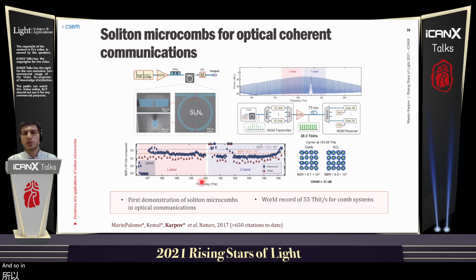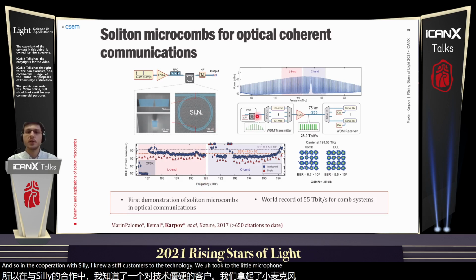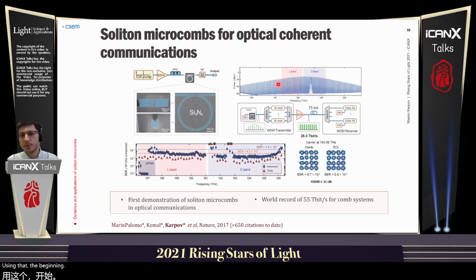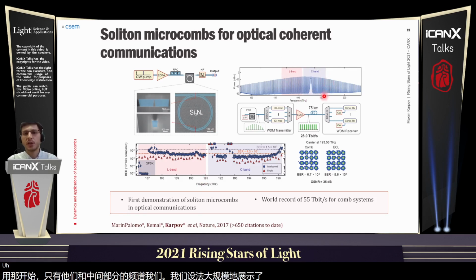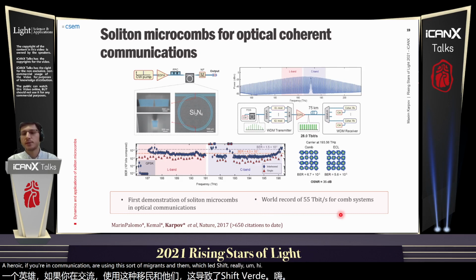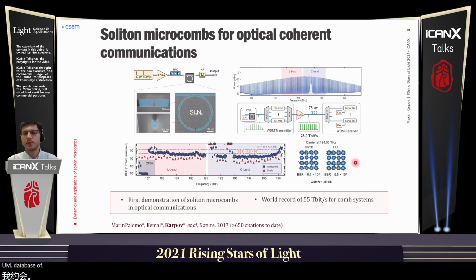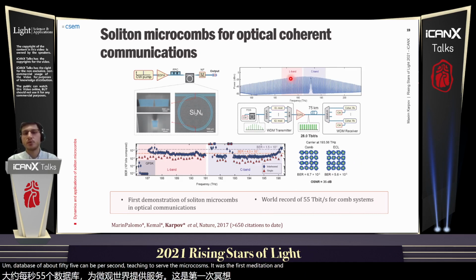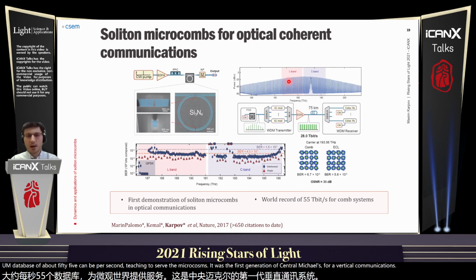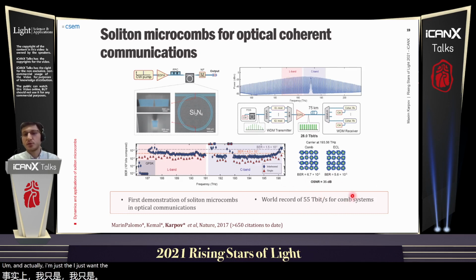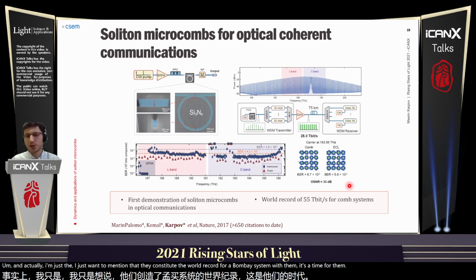And so in collaboration with the Karlsruhe Institute of Technology, we took two soliton microcombs and, using actually only the middle part of the spectrum, we managed to demonstrate massively parallel coherent communication using the soliton microcombs. We achieved really high accumulated data rates of about 55 terabit per second using two soliton microcombs. It was the first demonstration of soliton microcombs for optical communications. And I just wanted to mention that this was actually the world record for a comb-based system at the time for optical communications.